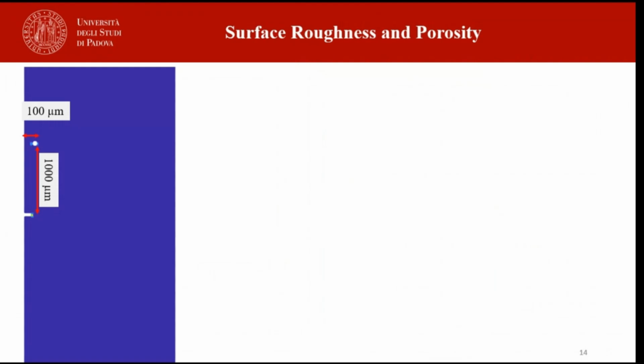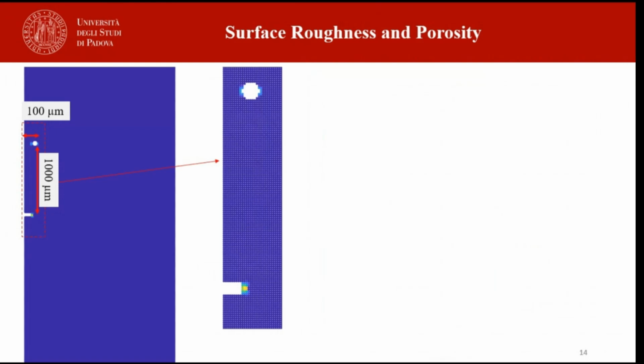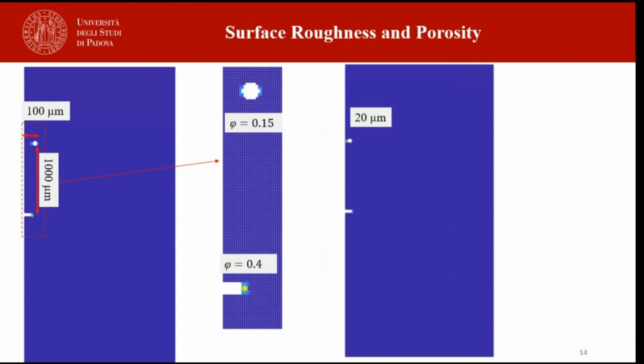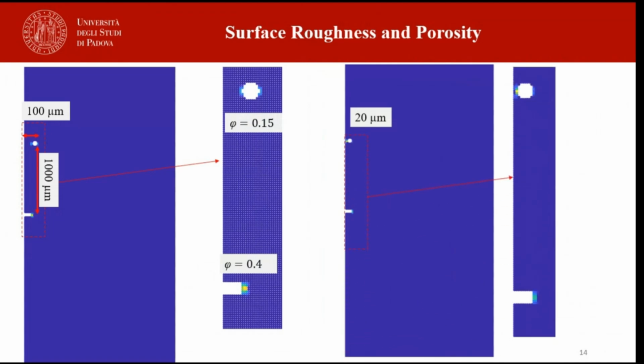When a pore is located at a distance of 100 micrometers from the free surface, the crack nucleates from both of them, but surface roughness dominates over porosity. It means that the crack here reached the growth stage earlier. Until 20 micrometers, surface roughness dominates over porosity, but at 20 micrometers, porosity dominates over surface roughness.